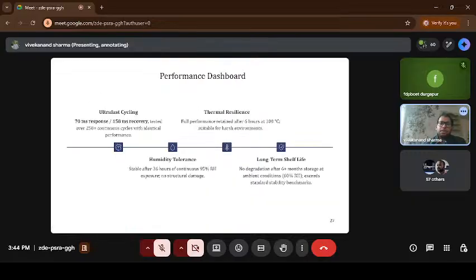Next, let's summarize the performance of this developed sensor. This sensor surpassed all of the currently reported humidity sensors utilized in our day-to-day life. The response cycle, from insulator to conductor, was only 70 milliseconds. It was very, very fast, even less than a second, just 0.07 seconds. And in just 158 milliseconds, it goes from conductive to non-conductive, which is called the recovery time. So it was hugely ultra fast.